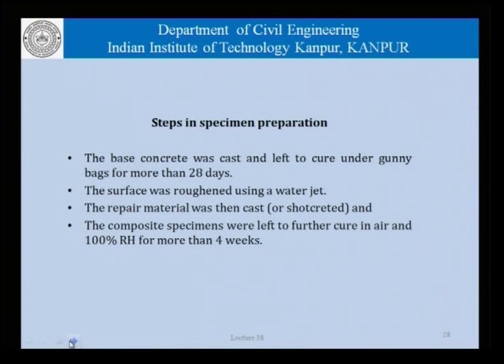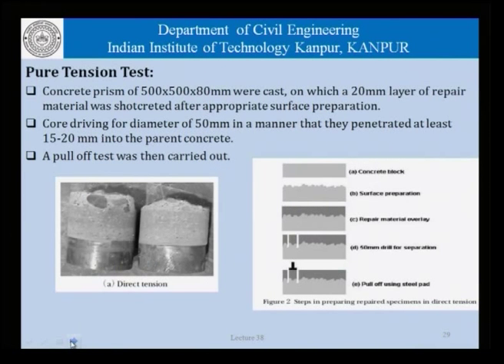Now, as far as the steps in the specimen preparation are concerned, there is the base concrete which is cast and left to cure under gunny bags for 28 days. The surface is roughened using a water jet. Repair material is cast or shotcreted, with the composite specimen being left to further cure in air for another 4 to 7 weeks. And in this case, different tests were carried out.